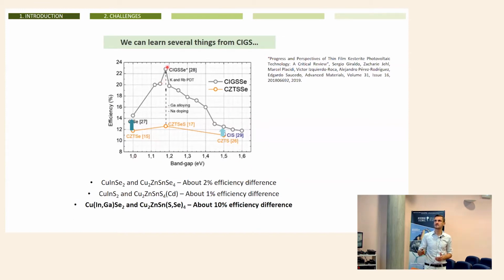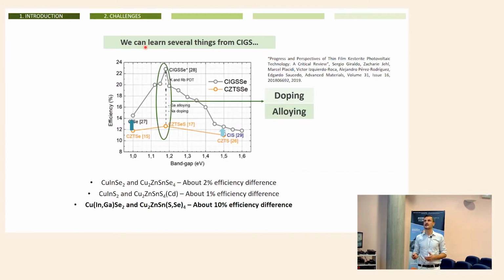Nevertheless, in this region that is the most interesting one for photovoltaic application, the difference is very high. And to go from 12–13% efficiency up to more than 20%, what CIGS adopted was doping process and alloying process. Doping with alkaline elements and alloying with gallium. Copper indium diselenide alloyed with gallium is a much better semiconductor than copper indium diselenide by itself.